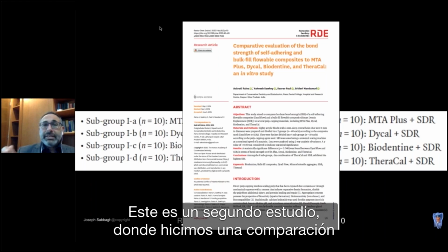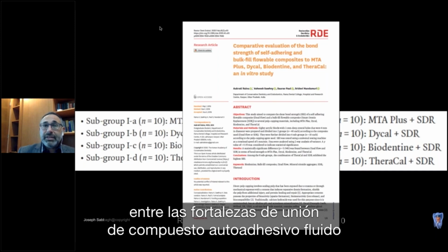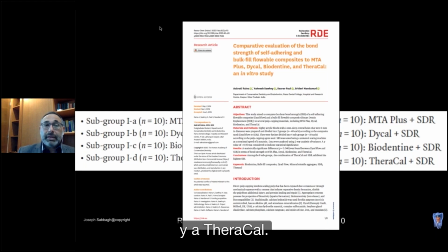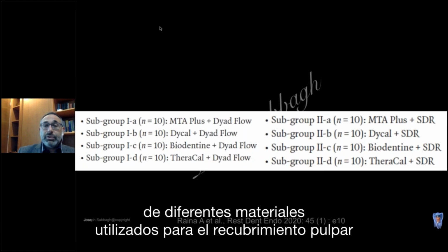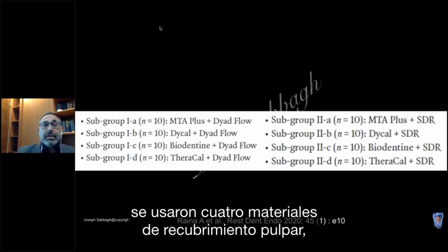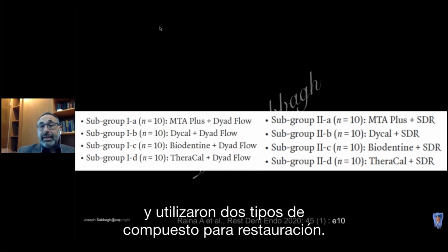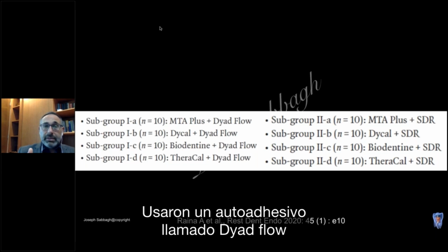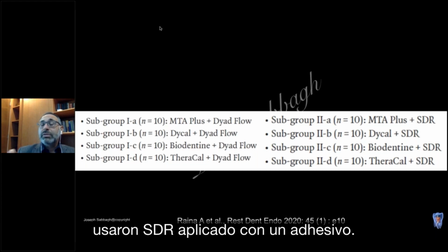This is a second study where we had a comparison between the bonding strengths of self-adhering bulk flowable composite to MTA, to Dycal, to Biodentine, and to TheraCal. This is also interesting because we have a wide variety of different materials used for pulp capping, including the biobulk, the Biodentine. So those are the four groups. They used four pulp capping materials, MTA, Dycal, Biodentine, and TheraCal, and they used two types of composite for restoration. They used a self-adhesive, that is the Dyad Flow, or the Vertise Flow in other countries. And in the other group, they used the SDR applied with an adhesive. And those are the results.